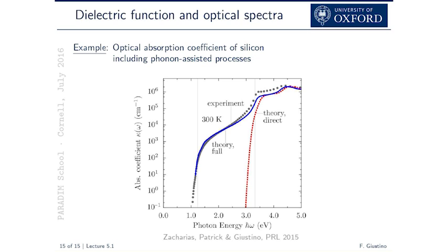So how can you deal with indirect absorption, and is that important? Well, if you think about silicon solar cells, all the absorption taking place in silicon is in this range, okay? Because basically the solar spectrum stops more or less here, so there is nothing here. So all of it is indirect absorption. So how to calculate that? That's quite a challenging problem, actually.